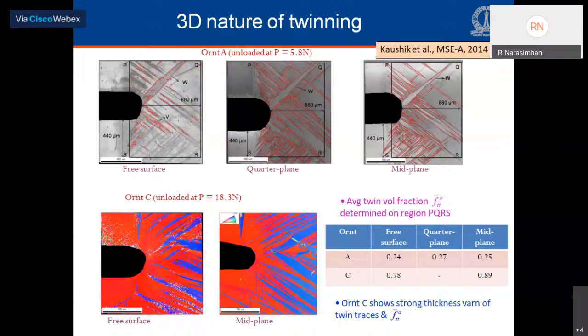I have shown here on the top sequence of images image quality maps from an unloaded specimen corresponding to orientation A, the free surface, the quarter plane, and the mid plane. And if you examine these images, you can see the pattern of twin development is very similar. There's not much thickness dependence. In fact, some of the twins like the W and V twin, which I showed in my earlier slide, they seem to persist all the way through the thickness.